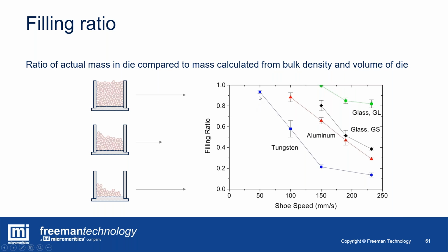And you can see the tungsten, this blue data set here, is actually reasonable at filling at particularly the lowest speed at 50 millimeters per second. It fills to about 95%, but very quickly reduces in terms of its filling efficiency as the shoe speed increases to 150 and then 230. In contrast, you've got the large glass beads. Even at 150 millimeters per second, it's pretty much filling to 100%, reducing only to about 82% at the highest speed.